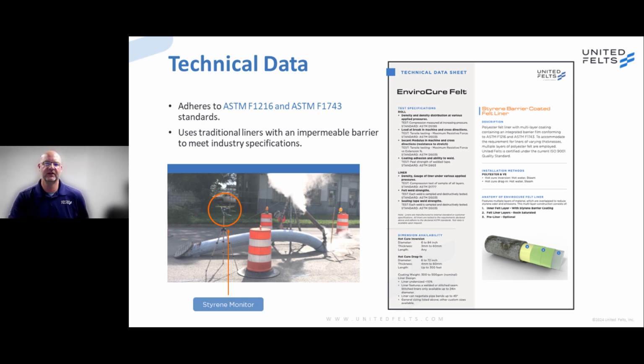So this material adheres to ASTM 1216 for inversion, as well as 1743 for pull-in applications. So this material behaves just like traditional liners. All we've done is incorporate a styrene barrier to limit the styrene emissions. And in the picture to the left, this was from one of our case studies we're going to get into in the next few slides. You can see the styrene monitor on site measuring styrene in the steam plume.